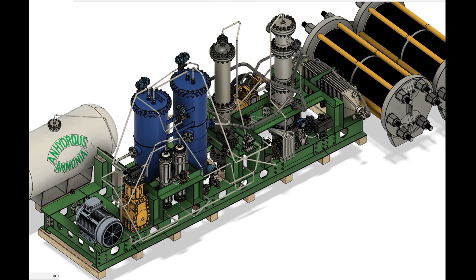Let's now compare the mass-catalyst ratio for a reactor sized for 40 kg NH3 per hour. For a 40 kg per hour reactor, with a catalyst activity of 1 kg NH3 per kilogram of catalyst per hour, the diameter is reduced to 0.38 meters, with a mass of 252 kilograms and a catalyst volume of 0.03 cubic meters. Note the mass-to-volume ratio remains constant as a function of scaling. The only scaling variable that is subject to nonlinear modification is the surface-to-volume ratio, caused by the square-cube law.